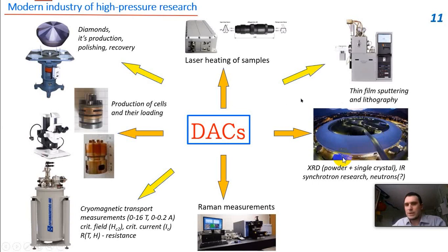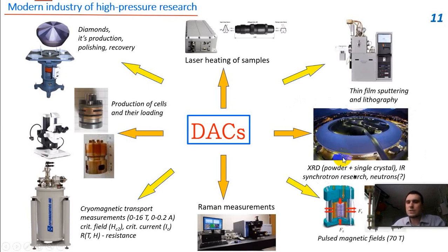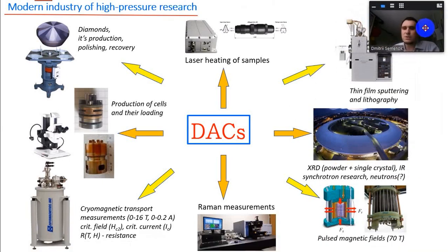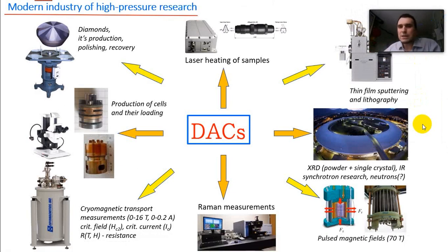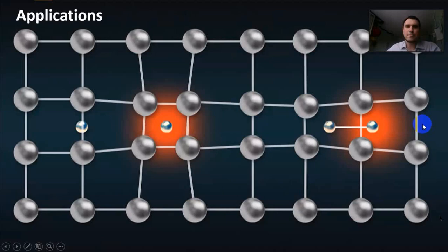Powder X-ray diffraction within this project was done abroad, outside of Russia, using European synchrotron sources such as ESRF and PETRA. And recently we started to use pulsed magnetic fields because hydride superconductors are high temperature superconductors, and they have quite a high upper critical magnetic field. So you cannot suppress superconductivity without using pulsed magnetic fields. Pulsed magnets do not exist in Russia. In order to use pulsed magnets, you need to go to other countries such as Germany. And in 2021, we worked about 1 month to study our samples in Dresden, Germany.